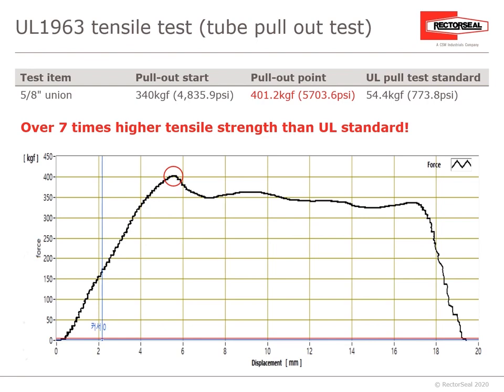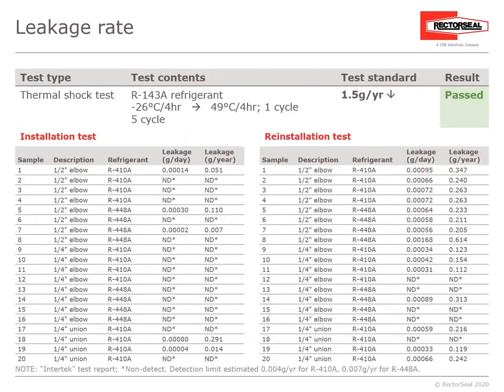That is, at which point does the ProFit Quick Connect fitting pull from the copper tubing. The UL pull test standard is 773.8 psi. The point at which the ProFit Quick Connect pulled from the copper tubing was more than 7 times that, at 5,703.6 psi. And finally, let's look at the leakage rate.